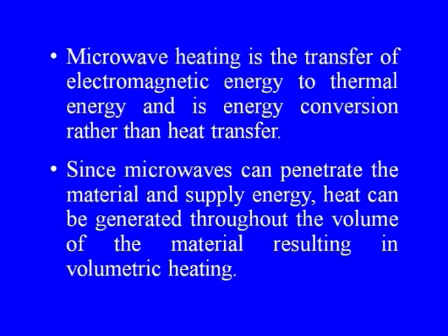Microwave heating is the transfer of electromagnetic energy to thermal energy and is energy conversion rather than heat transfer. Since microwaves can penetrate the material and supply energy, heat can be generated throughout the volume of the material, resulting in volumetric heating. This I have already discussed, how the entire volume of the material can get heated up, once the material is absorbing, of course.